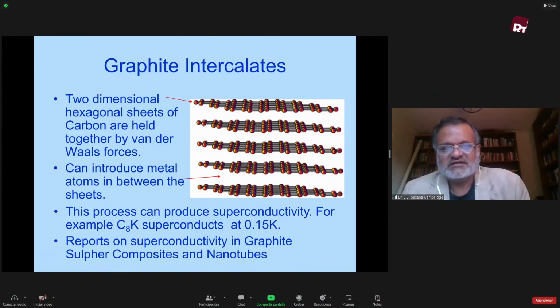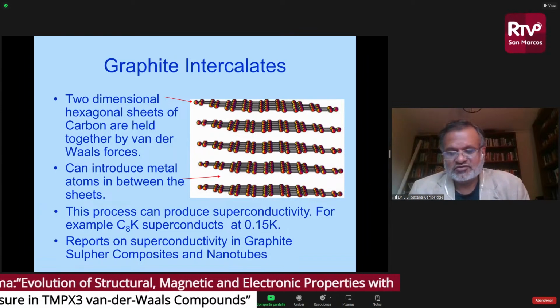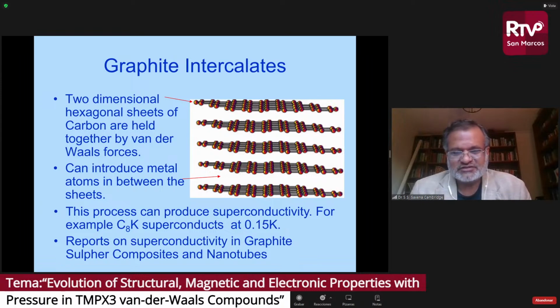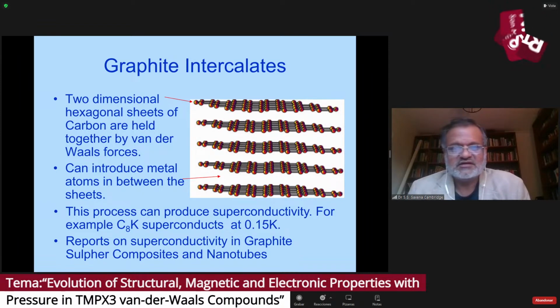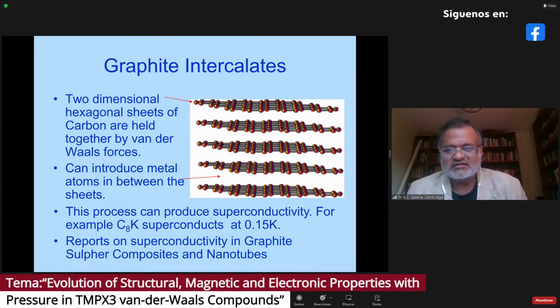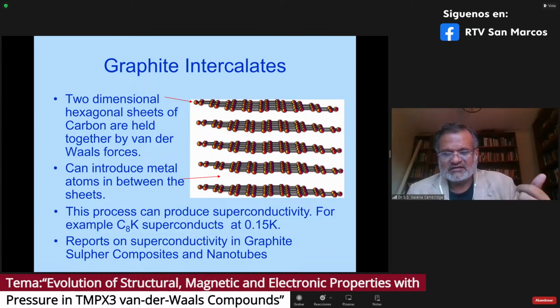So we started to imagine quite a while ago now whether we can recreate this kind of physics, more or less by hand, rather than relying just on nature to do its job. And the first thing that came to mind was graphite. The graphite intercalates are known to be superconducting, again at very low temperatures. But our story started with us trying to intercalate these materials with magnetic species, which can be tuned. So what we did was we put ytterbium into this, and created a ytterbium C6 compound, and the idea is that the hexagonal arrangement